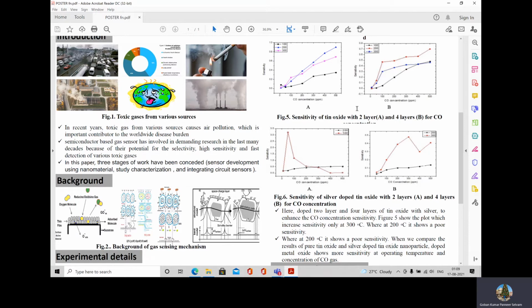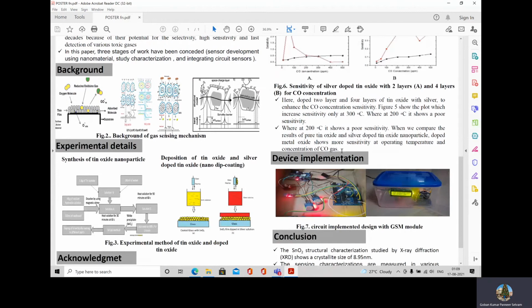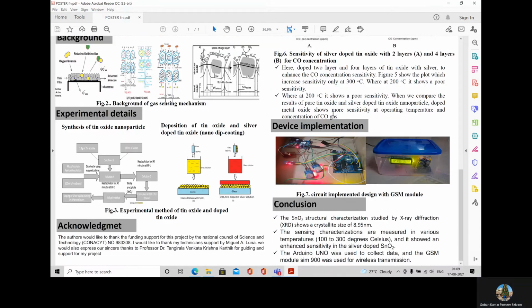Overall, we can see that tin oxide shows a good sensitivity, but the silver doped tin oxide shows a better sensitivity compared to the metal oxide semiconductor. When we compare the results of pure tin oxide and silver doped tin oxide nanomaterial, the doped metal oxide shows more sensitivity to operating temperature and the concentration of CO gas.